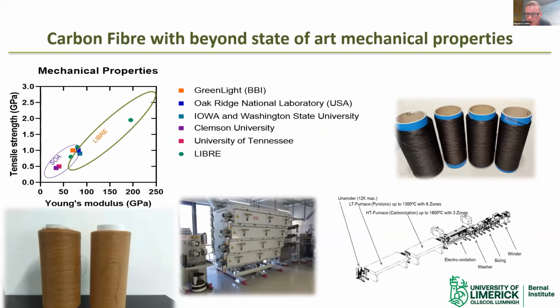Now this is one of my favorite slides. It shows the mechanical properties of our fibers. If you look at the tensile strength on the y-axis and modulus on the x, the state of the art is here for carbon fibers. The natural fibers themselves will be down at the bottom left-hand corner, but carbon fibers produced from bioresources would typically be about 100 gigapascal modulus and 1 gigapascal tensile strength. But you can see up here on the top right-hand side, this is the type of mechanical properties we were able to produce. So we got to 2 gigapascal tensile strength and 200 gigapascal modulus.